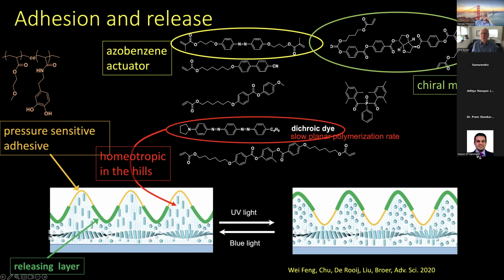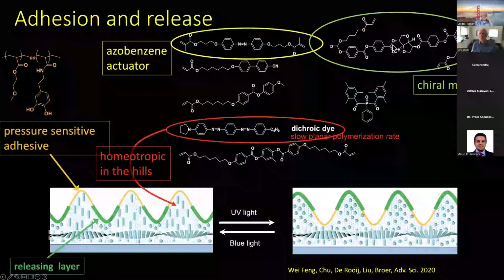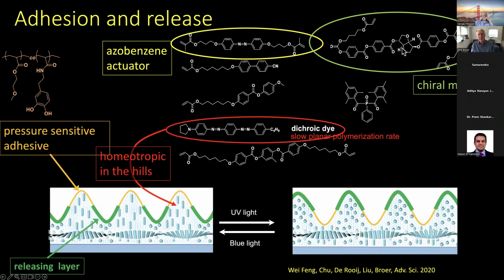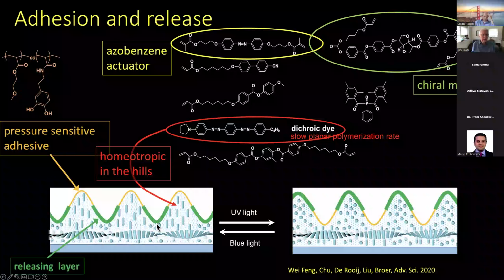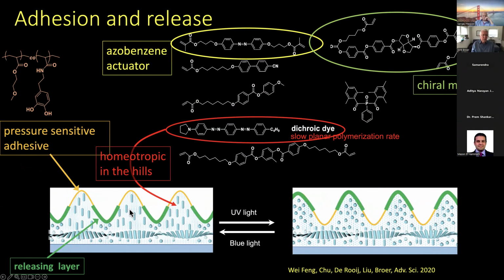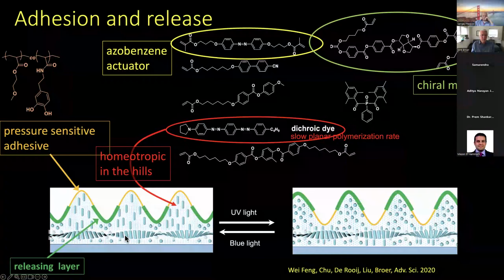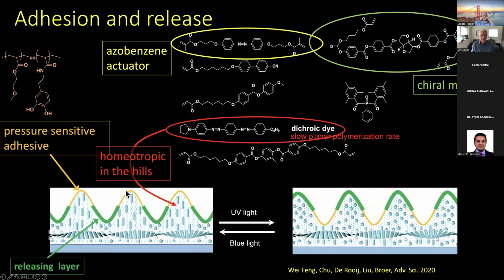So I help you a little bit through the composition. So again, we take the normal composition of liquid crystal monomers. We have added the chiral component to make it chiral, such that we get the thickness over pitch ratio correct. We have added the dichroic dye to slow down the polymerization in the planar areas, and we have added an azobenzene to make it actuate. So now, if we have polymerized it, we go from a state where we have the homeotropic areas in the hills and the planar areas in the valleys. And of course you can invert that by UV light.